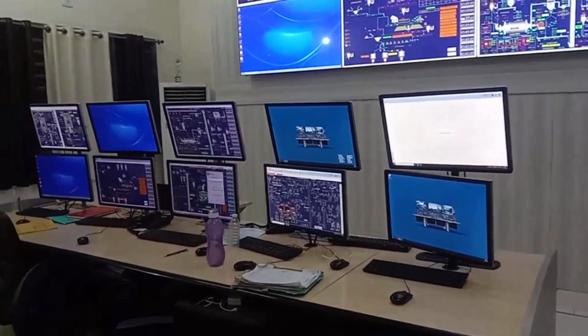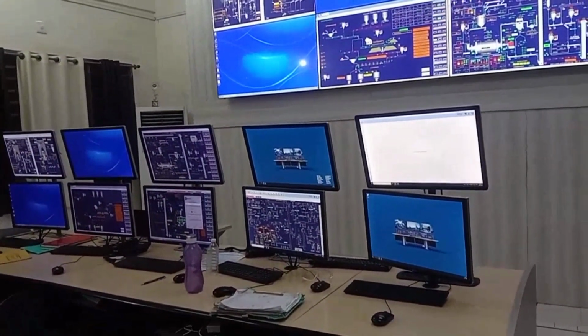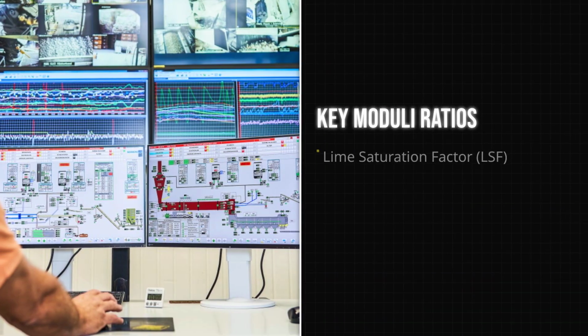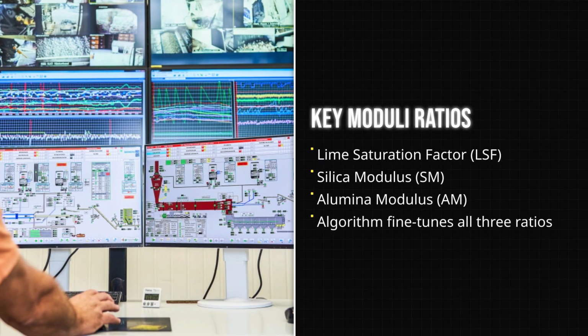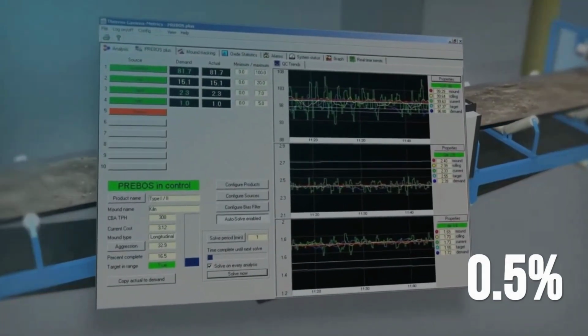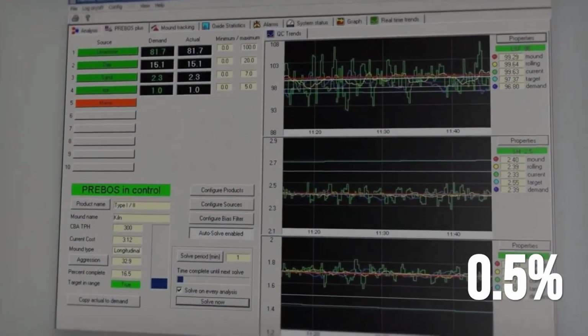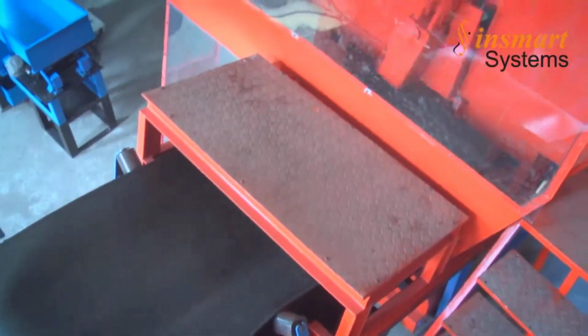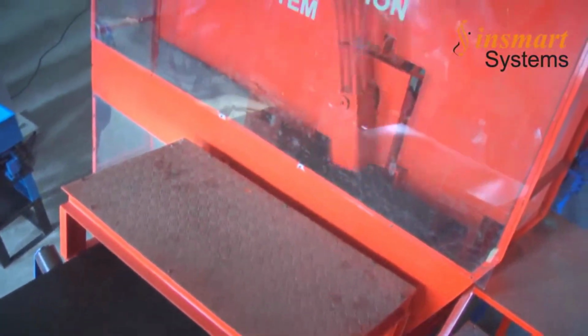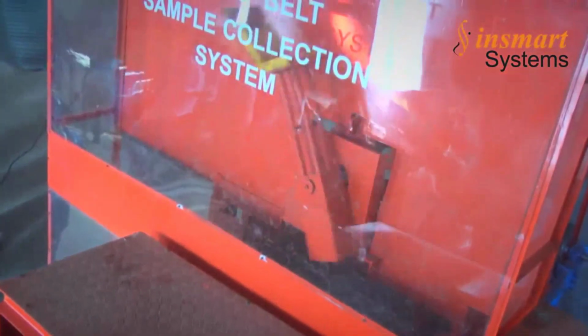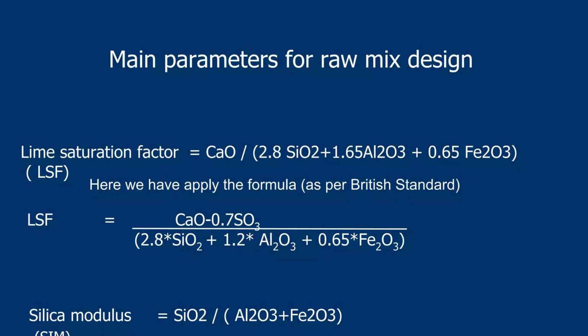On the control room's main display, 3 formulas dominate every decision: lime saturation factor, silica modulus, and alumina modulus. Each value is calculated in real time using the latest analyzer readings. Lime saturation factor, called LSF, is derived by dividing calcium oxide by a weighted sum of silicon dioxide, aluminum oxide,